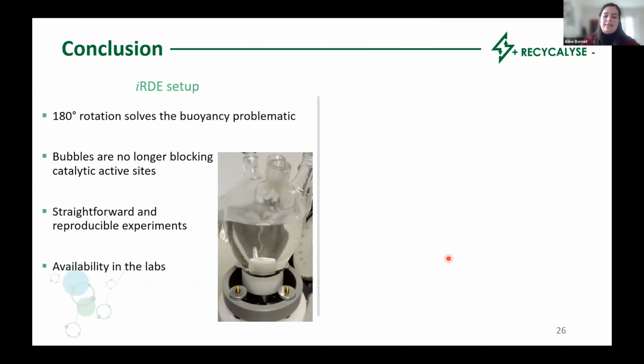And this makes a nice end to this presentation, where I introduced you to the revisited configuration of the traditional RDE setup. In this new configuration, the setup is rotated by 180 degrees, which allows the bubbles to detach from the electrode surface, as you can see here one more time on this video. And therefore, we can say that with this inverted configuration, the buoyancy problems that the traditional configuration faces are solved. And this setup is adequate for fast performance screening in the labs.